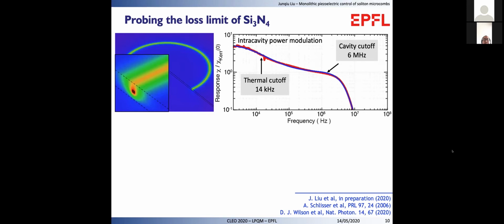Recently, we further performed experiment and simulation in order to understand, among the 6.5 MHz line width, how much is contributed by the scattering losses and how much is from thermal absorption losses. The method we use is to modulate the intracavity power and measure the resonance frequency shift in response to such intracavity power modulation. We have observed such a response curve which presents 2 cutoff frequencies. The cutoff frequency at 14 kHz is the thermal cutoff, limited by thermal conductivity and capacity of silicon nitride and silicon dioxide. The cutoff frequency at 6 MHz is the cavity line width cutoff.